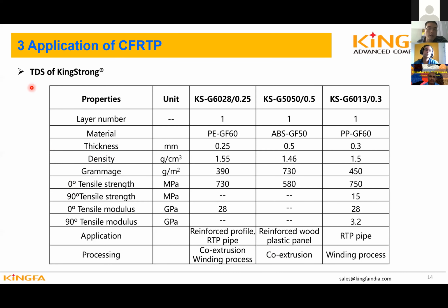Here are some properties of our UD tape. We have polyethylene, ABS, and polypropylene. We can see at 0 degree, along the glass fiber direction, the tensile strength is very high. It's about 730, 580, and 750 with different glass fiber. But at 90 degree, because there's no fiber reinforcement, the property is close to the resin property. So for this kind of UD tape, we can use it for co-extrusion and the winding process.